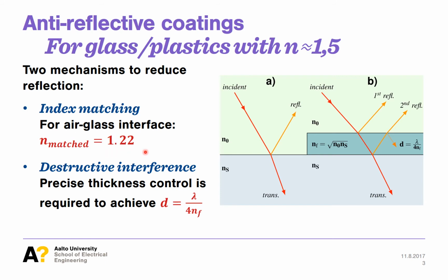It is possible to further decrease reflection by carefully choosing the thickness of the film to achieve destructive interference between the two reflected waves, which you can see in the picture, the first wave and the second wave. Destructive interference occurs when these two waves have a phase difference of pi. In order to have such a situation, the film thickness should have a value of wavelength divided by 4 times the refractive index of the film for normal incidence of light.